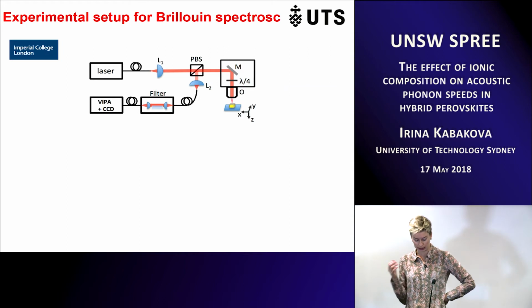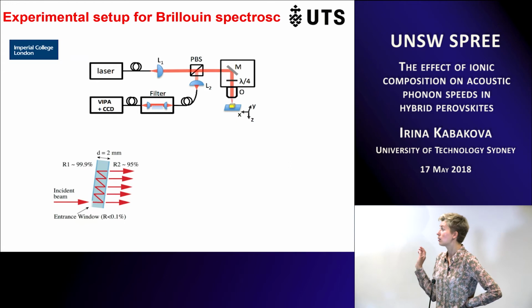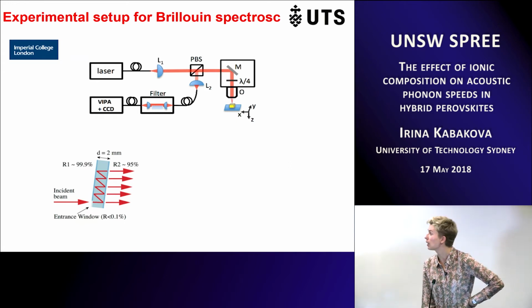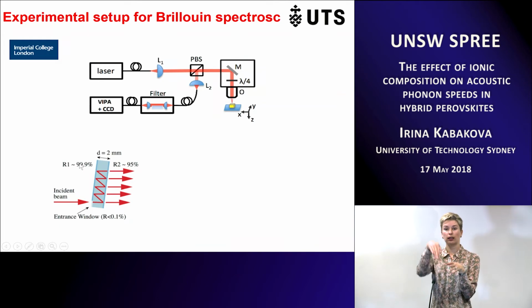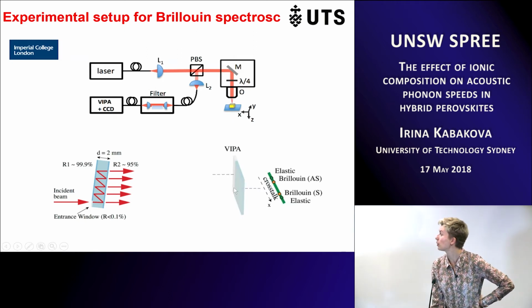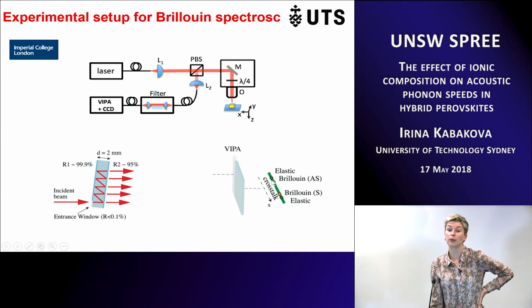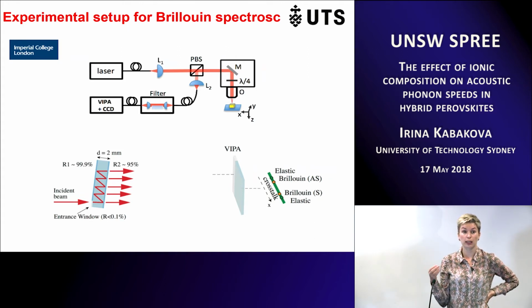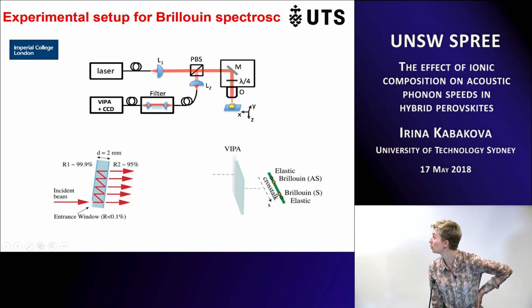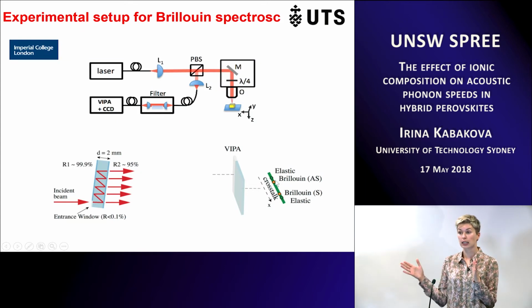The spectrometer is actually quite a simple device, which is called a virtually imaged phased array, and it's nothing else than a Fabry-Perot, which is put at a slight angle, about 1 degree, and has coatings on it. It has a transparency window here, a complete reflection coating here, and a slightly transmissive coating here. So it takes all of the light and disperses it at an angle with regard to the frequency of the light. So what you end up with are diffraction orders. For each order, you have an elastic peak, which is Rayleigh scattering, the scattering at the same frequency as the incoming light. And you have these new peaks next to Rayleigh, which are called Brillouin peaks, which are frequency shifted. And the frequency shift, as I mentioned already, is proportional to the acoustic velocity.